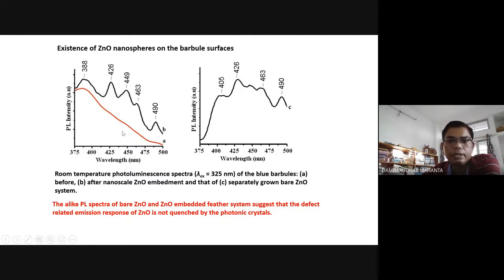The red one being the spectra for the feather. Now in this case, after loading we found that there is a change in the spectra, but these positions also remained intact. So it means zinc oxide is actually present on this organic stuff which is the feather, and zinc oxide is indeed loaded on the feather.